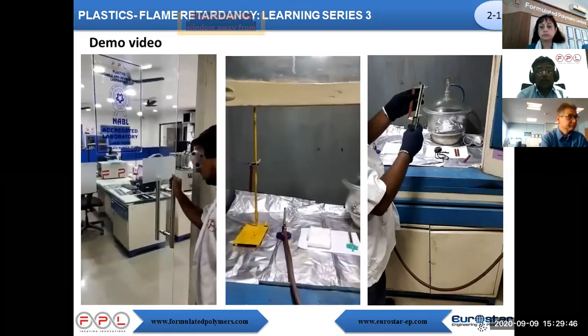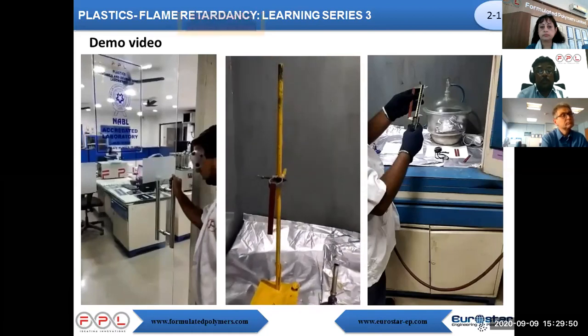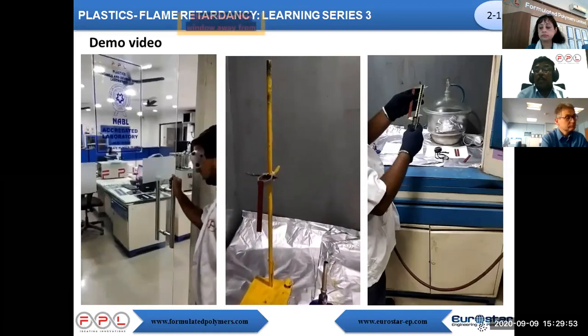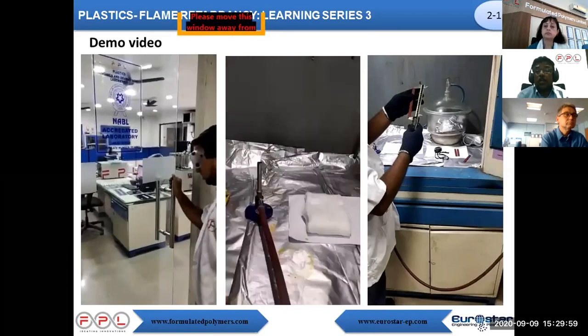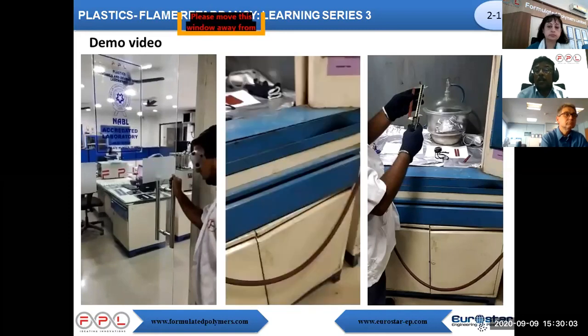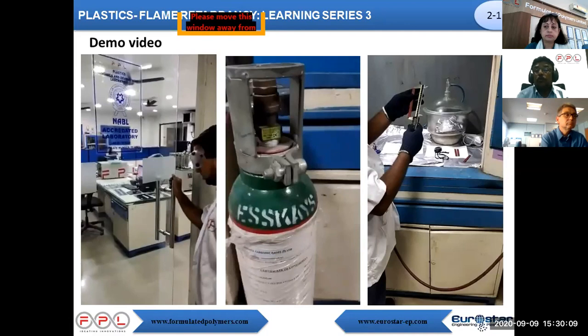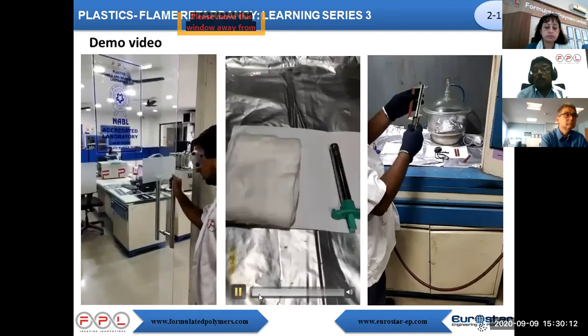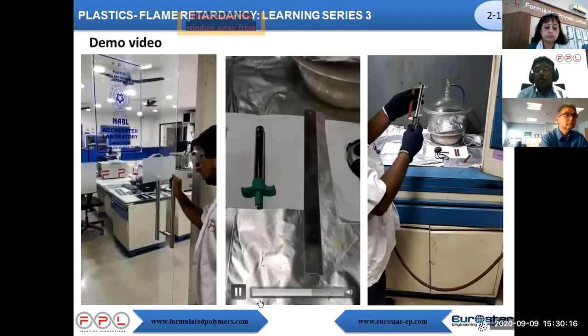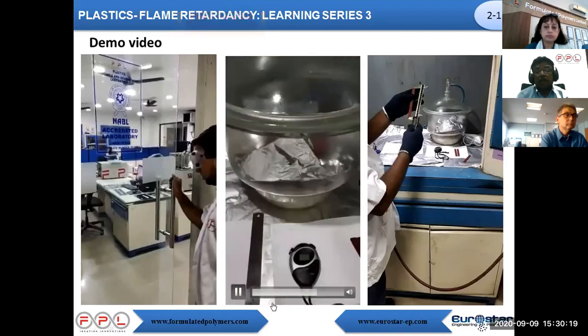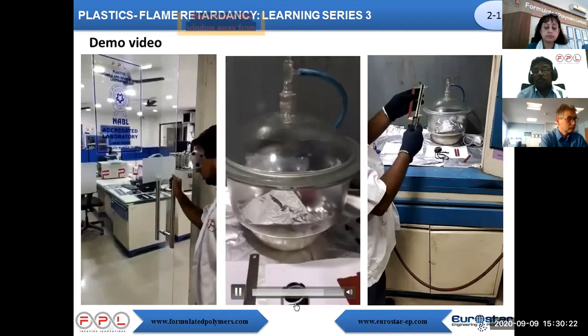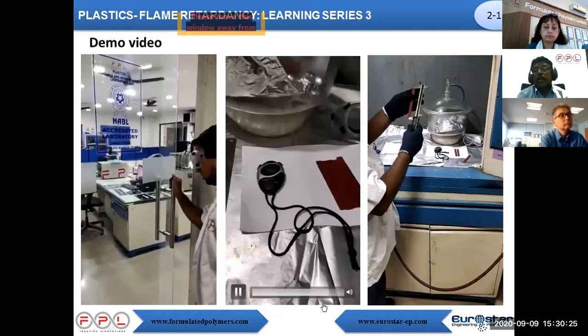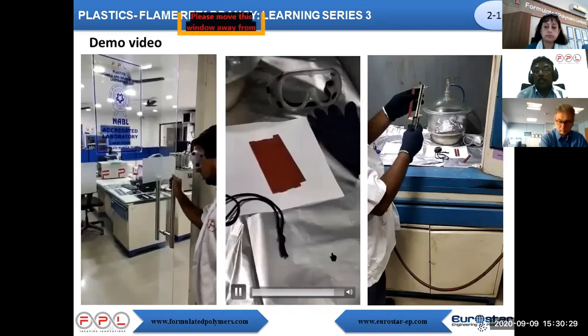Next part, apparatus required for the test. To do the UL94 vertical burning test, we need a laboratory fume hood with proper exhaust facilities, then a specimen holder, then a Bunsen burner with wire at required length. Then we need methane gas supply of 98% purity, then 100% absorbent cotton bed, then an ignition source, a measuring scale, and a timing device of accuracy 0.1 seconds. Of course, specimens need to be annealed using a desiccator. Then finally, we need PPE of gloves and goggles.